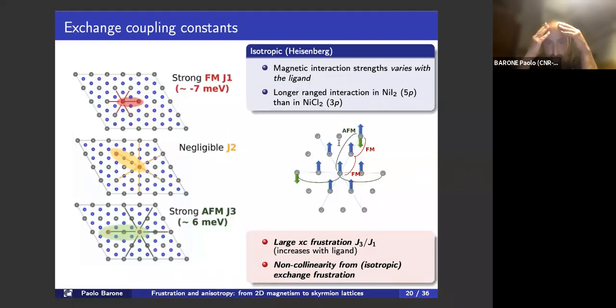Okay, so the first thing we did was to estimate the isotropic exchange coupling constants. And basically, we see consistent trends in the three materials we considered. There is a very strong ferromagnetic nearest neighbor interaction, as in the chromium iodide system. We find a negligible second nearest neighbor interaction, whereas what was kind of surprising for us at the beginning was that we found a very strong antiferromagnetic third nearest neighbor interaction, whose strength increases with the size of the ligand.